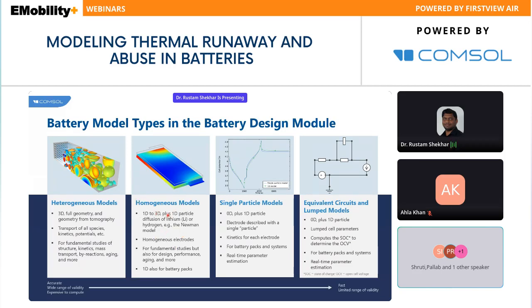In some cases you want to model the particle cracking, so that will be handled by the heterogeneous and homogeneous models. And the difference that you can see between heterogeneous and homogeneous is, in homogeneous, you are not modeling the particle, you are just accounting for the intercalation. But in heterogeneous, you can exactly take the same electrode geometry and work on that. So you can import the 3D geometry tomography data, and then you can work with that. So this is how you can work with homogeneous and heterogeneous models.